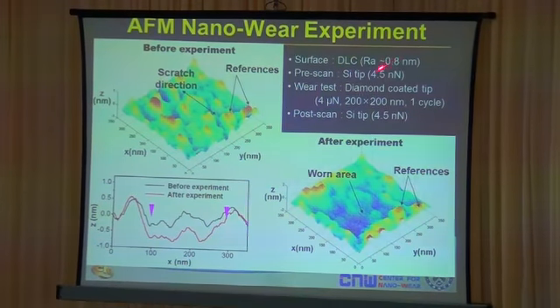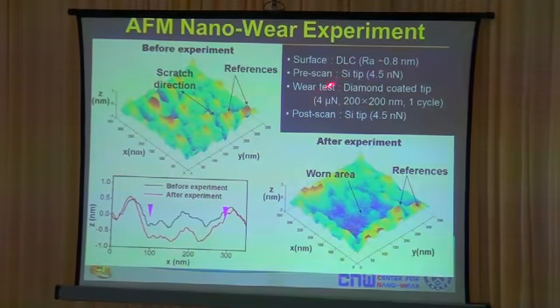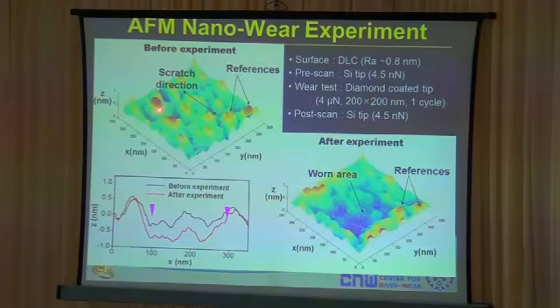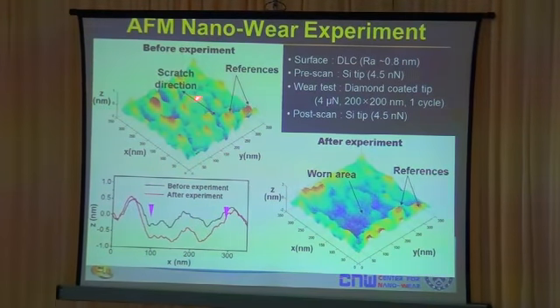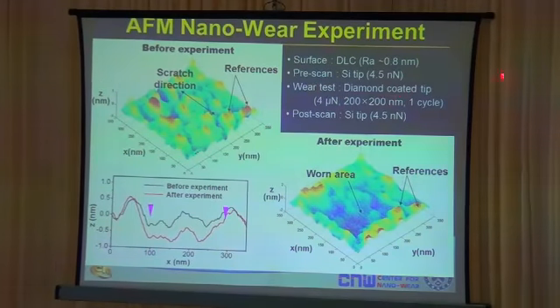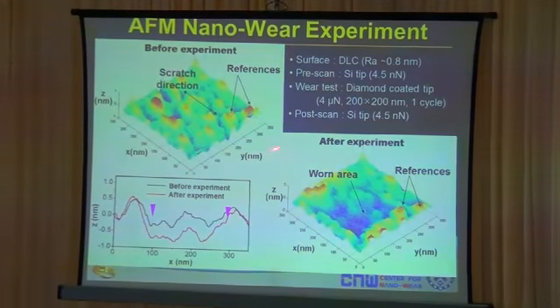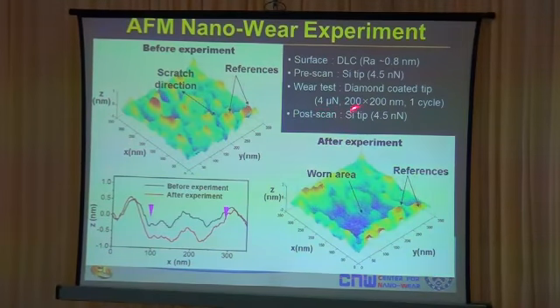What you're looking at here is an AFM experiment that was conducted on a diamond-like carbon film with a surface roughness of 0.8 nanometers. First, you pre-scan the surface using 4.5 nanonewtons, and this is what the surface looks like before the wear test. Without removing the specimen from your AFM, you take a diamond tip and scan the surface to do your wear test under 4 micronewtons, over 1 cycle. After the wear test, you change back to your silicon tip and post-scan to image the surface. This is the image you get after the wear test, and this is the image you get before the wear test.